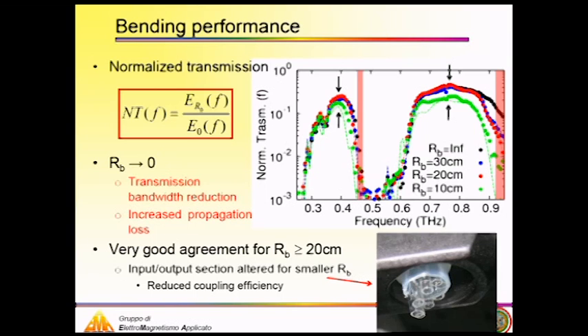And as you can see, there are two main effects that are connected to the bending. The first one, highlighted with this red region, is a slight reduction of the transmission bandwidth for both transmission windows, and also an increase of the propagation loss in the middle of both transmission windows. Well, the agreement with the numerical results is still good. However, we found some discrepancy for the 10 centimeter bending case, and we think that, as you can see from this picture, this might be due to the fact that for such a tight bending, the input and output parts of the fiber are strongly perturbed, and this may alter the input and output coupling efficiency of the fiber, thus perturbing the results.